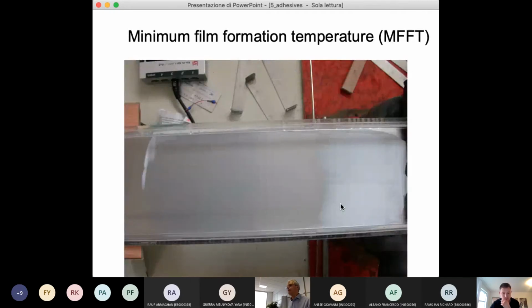And so this is really the last image I would like to show to you. This is a film of a dispersion adhesive which was applied on this steel plate with a gradient of temperature. Here we had -20. Here we had +20 degrees. And you see that in this part, the adhesive is completely white, and here the adhesive is transparent. So here the coalescence was good. In that part, the coalescence was not right, didn't happen.